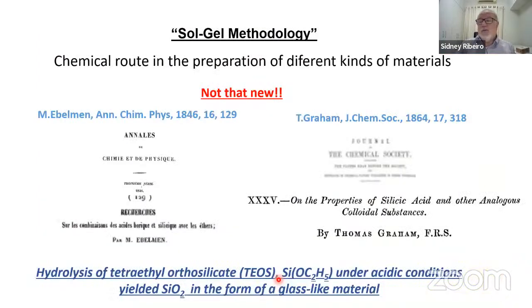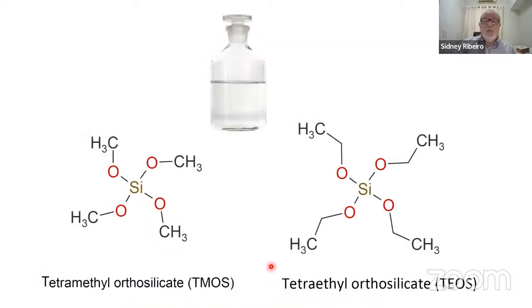Then we are talking about sol-gel, doing the same materials at low temperatures. And I must say that these methods are not that new. The first papers on this were published in the 19th century. These papers deal with the liquid precursor. They establish that under acidic conditions, this precursor leads to silica in the form of a glass-like material. So this is a low temperature route leading to silica. These are our famous liquid precursors, TEOS, tetraethyl orthosilicate, and TMOS, tetramethyl orthosilicate. These are alkoxides, liquids, for which we control the hydrolysis and condensation to obtain our macroscopic materials.